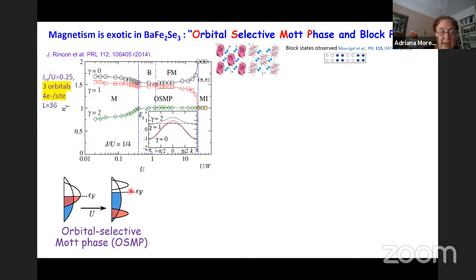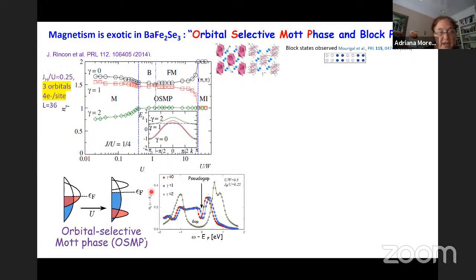We calculated the density of states with DMRG, and this is exactly what happens: the green orbital develops a gap, while the blue and red orbitals remain metallic, although they develop a pseudo gap at the chemical potential. This again is due to the interactions, but we still cannot really explain why the pseudo gap happens. The behavior resembles the cartoon very much.